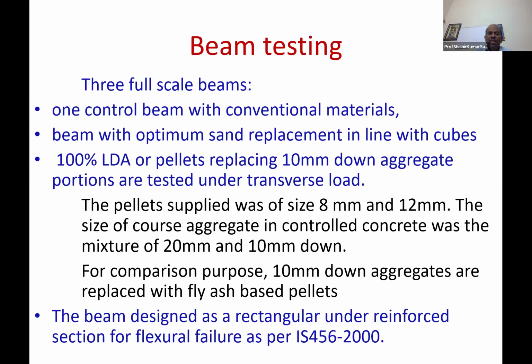Then beam testing. Full-scale beams are also tested. One control beam with conventional materials and a beam with optimum sand replacement, in line with 100% pellets also used, replacing 10 millimeter down aggregates. The pellet supplied was of 8 millimeter and 12 millimeter size, against coarse aggregate in the control concrete mixture of 20 mm and 10 mm down. For comparison purposes, 10 mm down aggregates were replaced with fly ash based pellets.